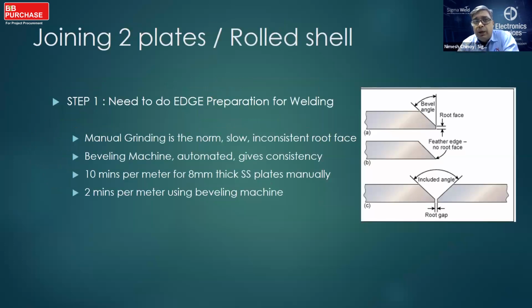When you decide to do any kind of welding on a plate or a rolled shell, you have to make an edge preparation. That means you have to spend time creating the right bevel angle and the root face. If you do it manually using grinding, it's normally slow and gives inconsistent root faces. But if you do it with a machine, that is a beveling machine or a milling machine, you will always have consistency on the bevel angle and root face.